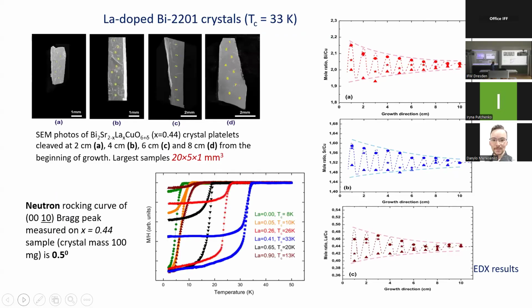This is lanthanum-doped bismuth 2201. The growth is very similar to the undoped system, although lanthanum substitution increases TC up to 33, 35K. And we could grow really large samples, with a good crystallinity that was confirmed by neutron diffraction, although even the best crystals have a certain composition inhomogeneity. And if you look at the magnetization curves, they're relatively broad. So still it is a problem for this system.